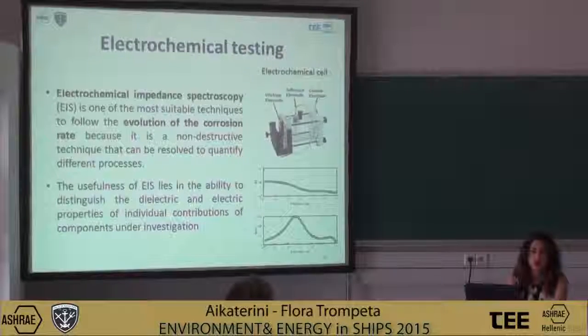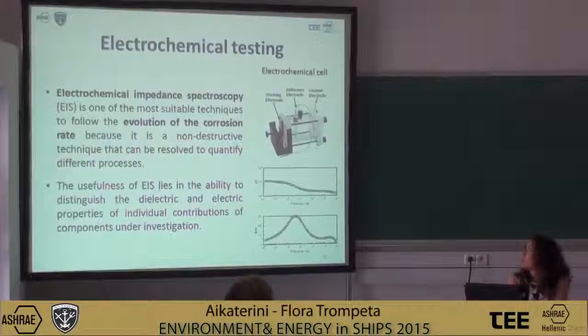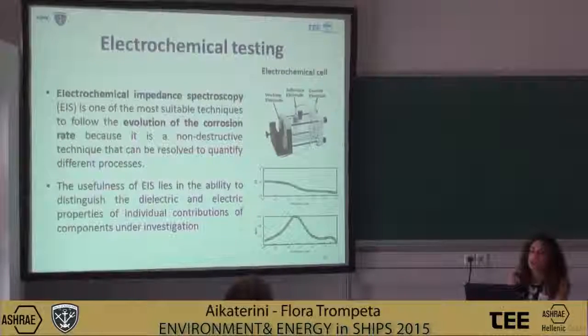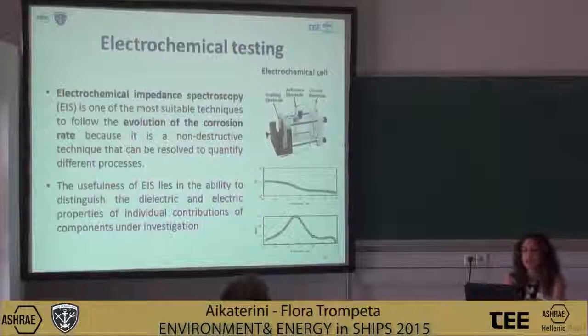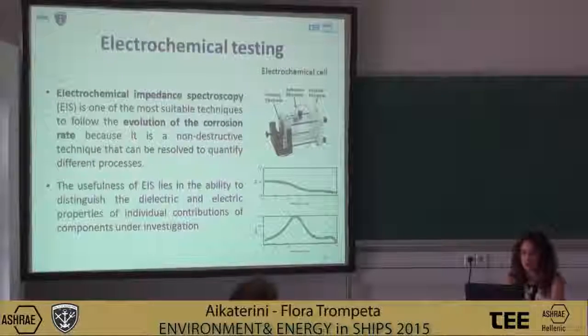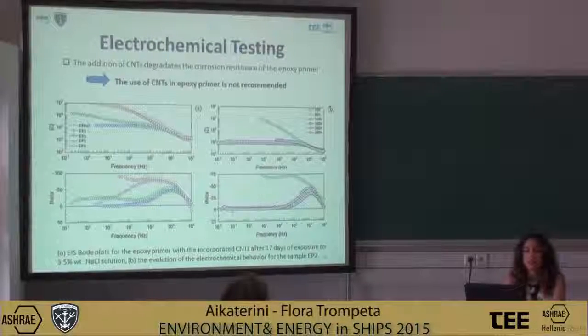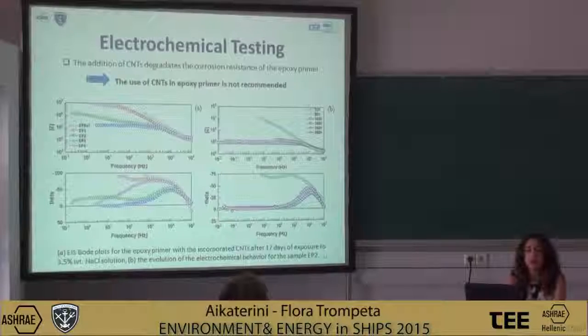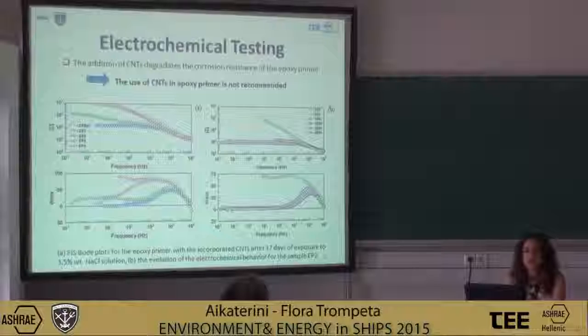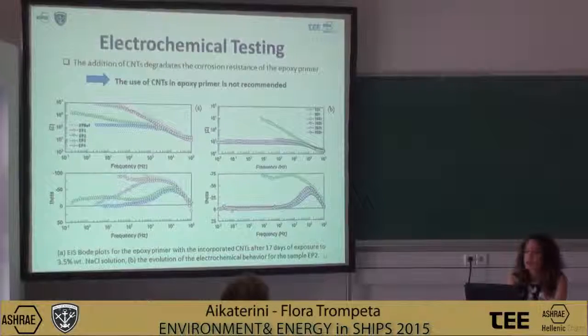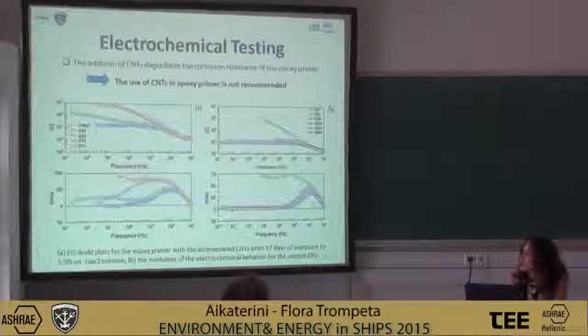To perform the measurements, an electrochemical cell is needed, and we use 3 different electrodes: a working electrode, a reference electrode, and the counter electrode. The results of the electrochemical testing were that the addition of the CNTs degraded the corrosion resistance of the epoxy primer. This can be seen from the Bode plots here.